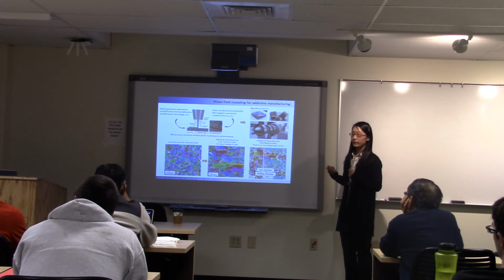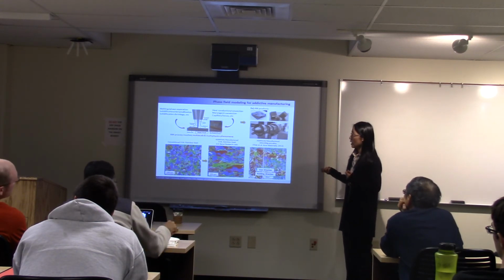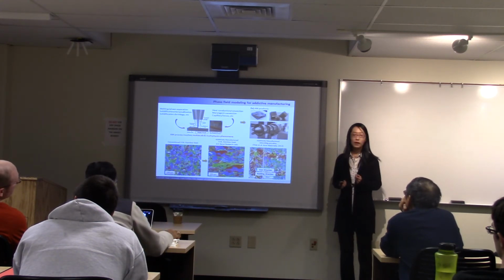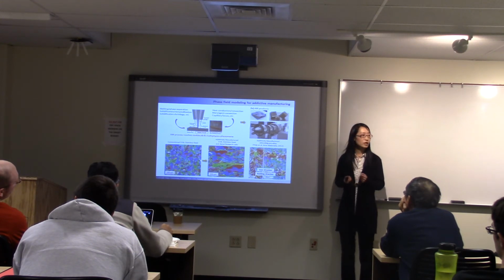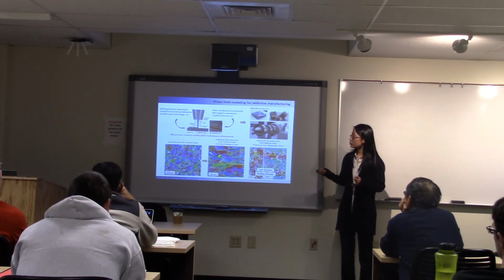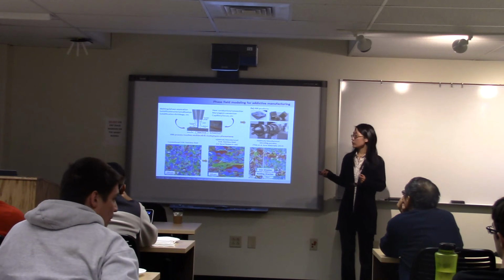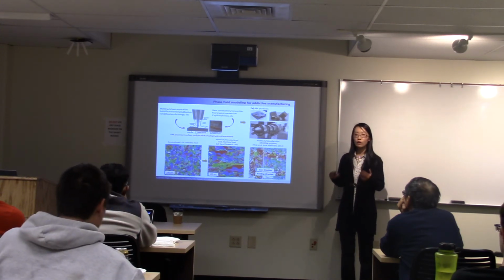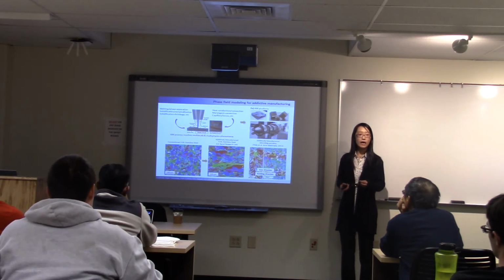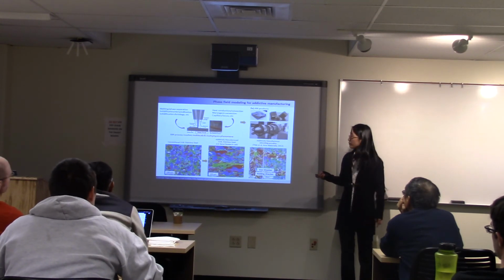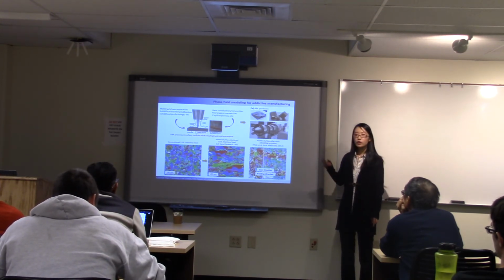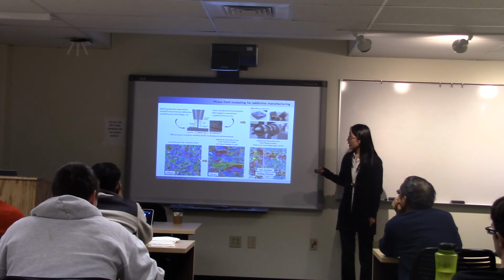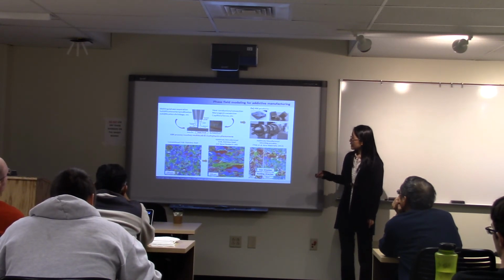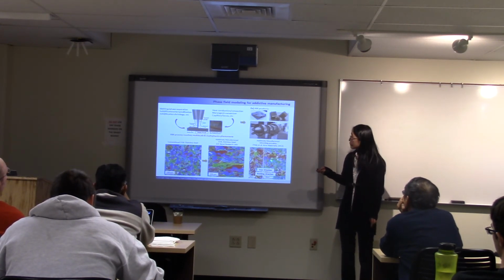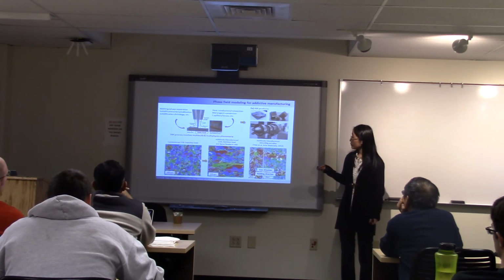So these are the experimental results we got from our collaborator at the Naval Research Laboratory, and we find there's a drastic change of the microstructure compared with the conventional process for 316L stainless steel, featured by highly non-uniform grain size as well as irregular grains. And there's another published work on a similar material. We can find there's a wide distribution of the grain size.